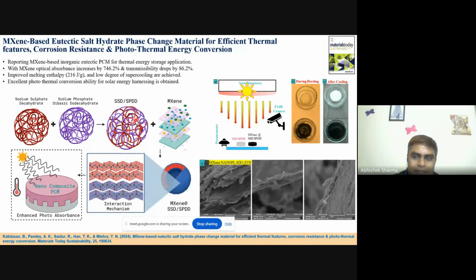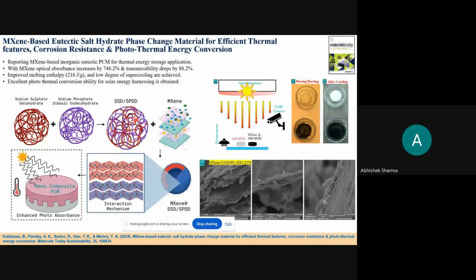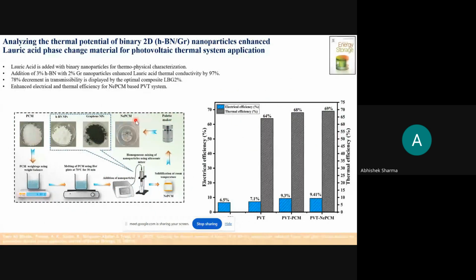What we found is that optical absorbance was improved by more than 700%, transmissibility dropped by 86%, and the enthalpy was improved. The degree of supercooling was improved. But as far as the thermal conductivity, the results were not as encouraging as we were expecting. Electrical conductivity is very good, but thermal conductivity may not be that good, especially for this type of material. But as I said, it's a matter of further investigation for other phase change materials.